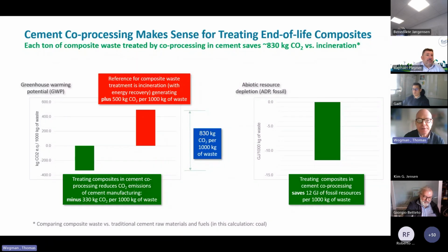If you compare that with the reference for composite waste treatment, which we believe is incineration with energy recovery, that process generates plus 500 kilograms of CO2 per 1 ton of waste, because you have to burn the material in the waste incineration plant. So the difference between the two is 830. That's what we see as a nice difference of what we would save. Again, the 500 kilograms is also the average for the different waste profiles. I'll come back to that in a minute.